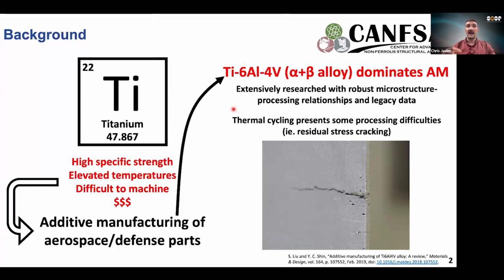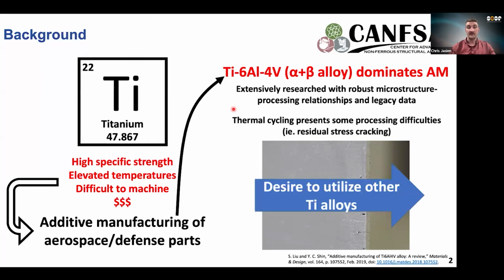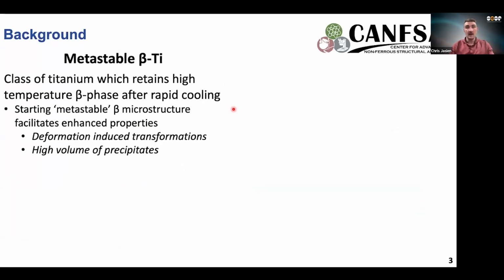With additive manufacturing or 3D printing, you rapidly heat and cool your material. This creates lots of temperature fluctuations, which can then cause processing difficulties, such as residual stress cracking. So there's a desire within the Department of Energy to understand how we can utilize other Ti alloys to get these benefits while mitigating some of these cracking issues. The one class which has shown the most promise is called metastable beta Ti. It's a separate class of titanium alloys which can retain the high temperature beta phase after it's rapidly cooled. After you quickly cool it, it can metastably maintain this structure.